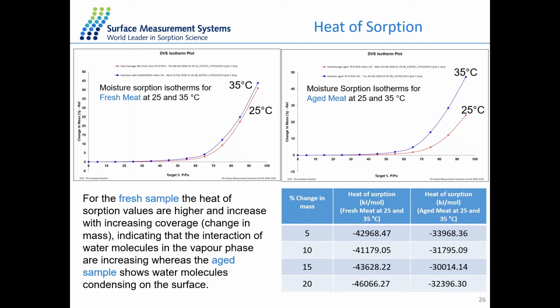And the heat of sorption is also increasing with the increasing of the coverage for the fresh meat sample, which indicates the interaction between the water and fresh meat sample is also increasing. Well, for the aged sample, the value is much smaller and it doesn't increase at all. That means it's also close to the heat of evaporation for the water molecule.